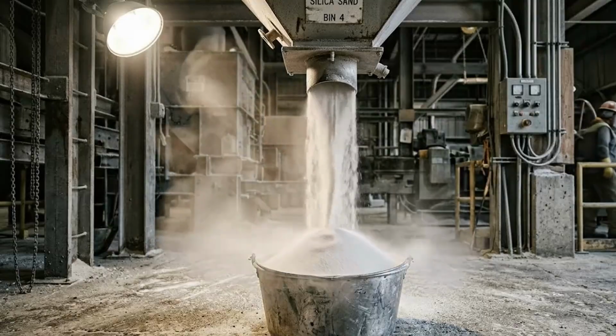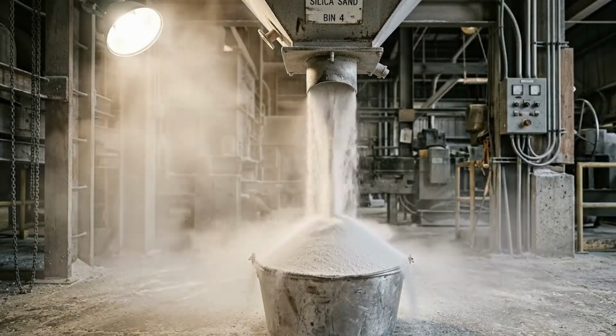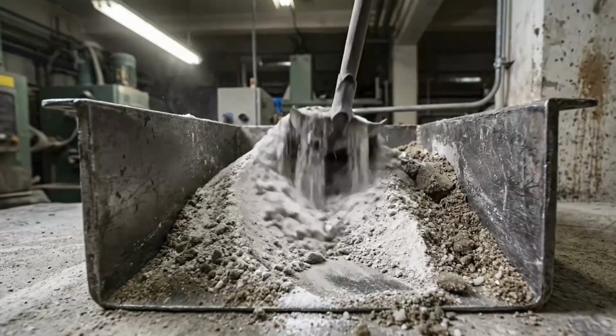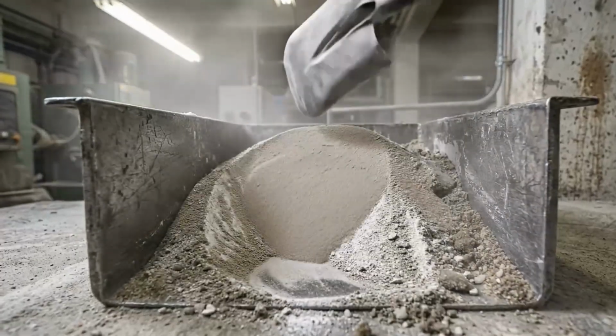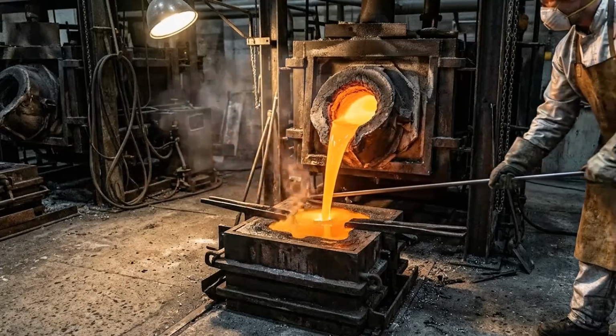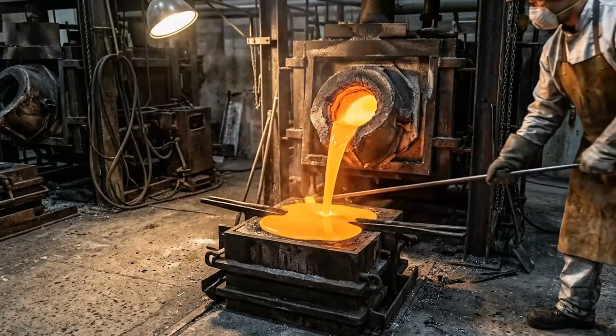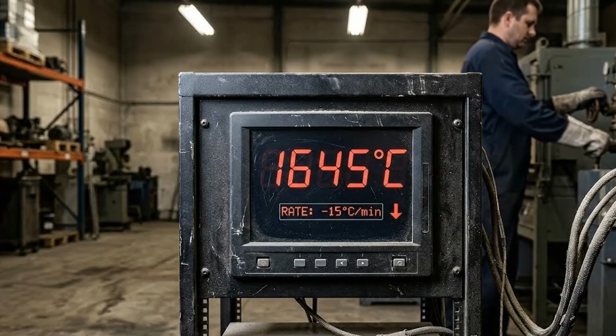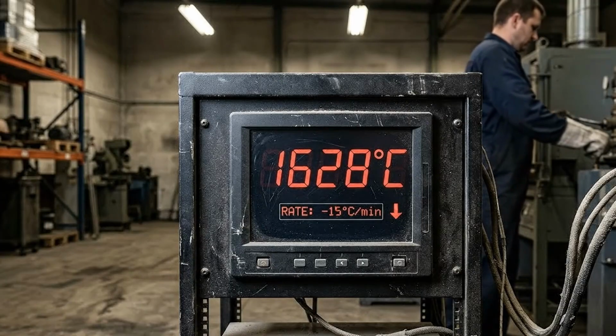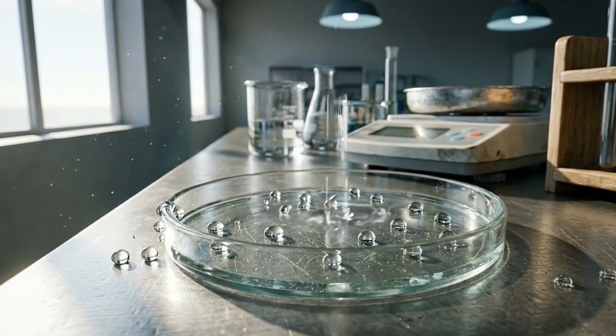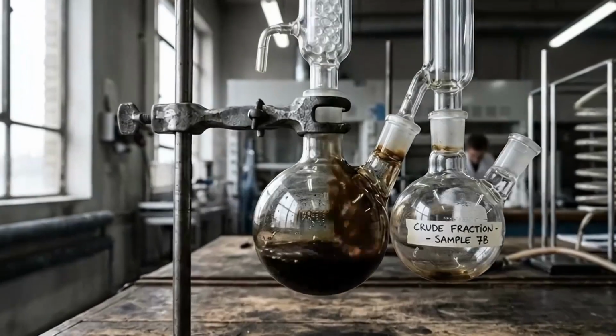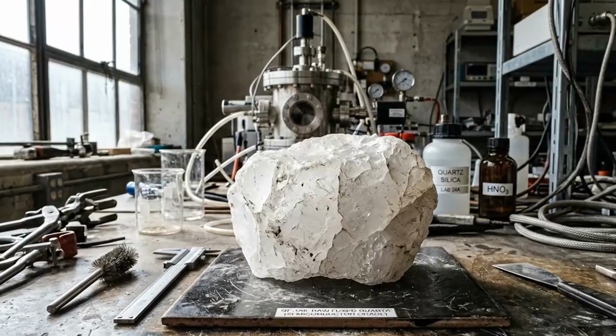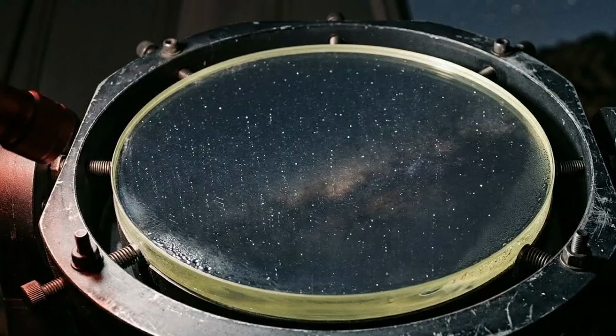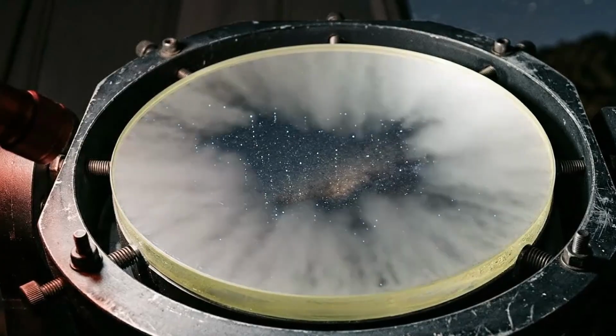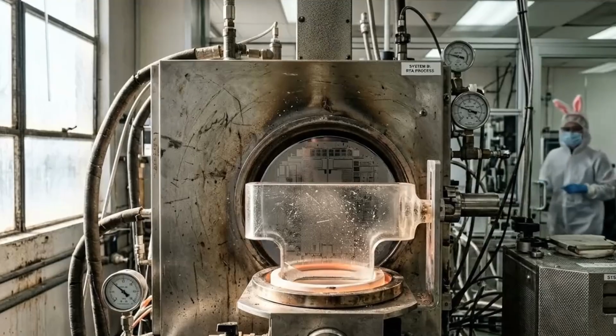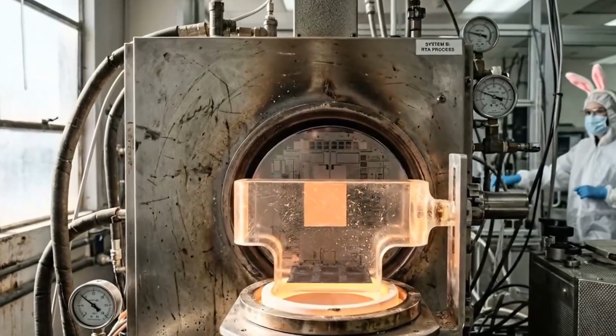Ordinary soda-lime glass, the kind in your windows, is about 70 to 75% silica, sand, plus soda ash, sodium carbonate, and lime, calcium oxide. The soda lowers the melting point from approximately 1,700 degrees Celsius to approximately 1,500 degrees Celsius, making it practical to produce. The lime makes it more durable and water-resistant. Without those additives, pure silica glass, fused quartz, would be too expensive and hard to work with for everyday use. But it's used in high-end applications, telescope mirrors, UV lamps, semiconductor manufacturing, because it has almost zero thermal expansion.